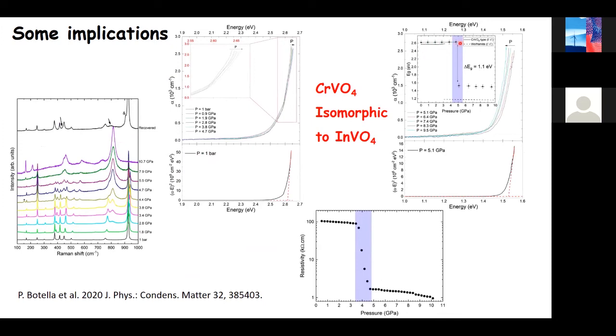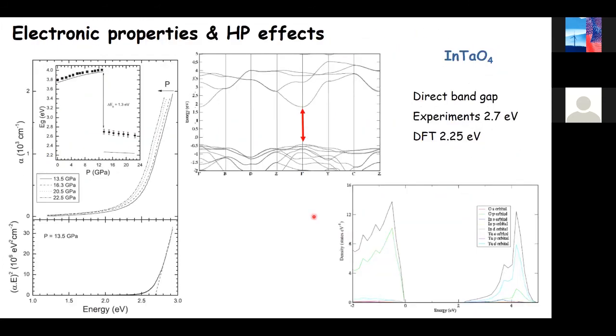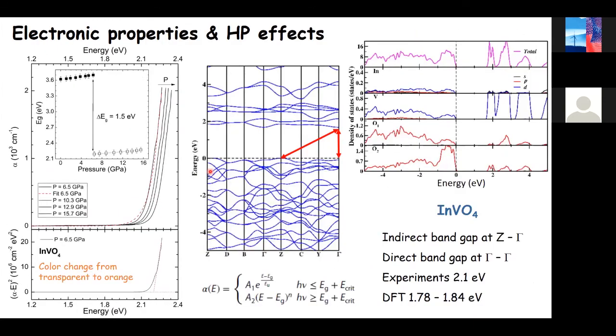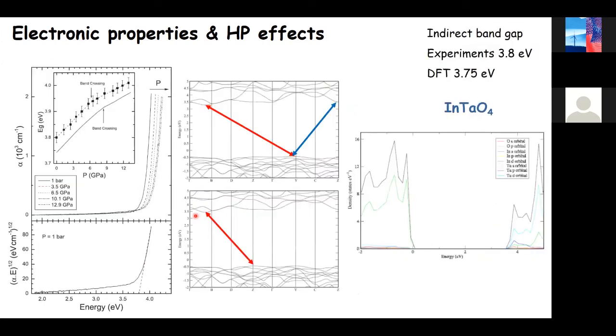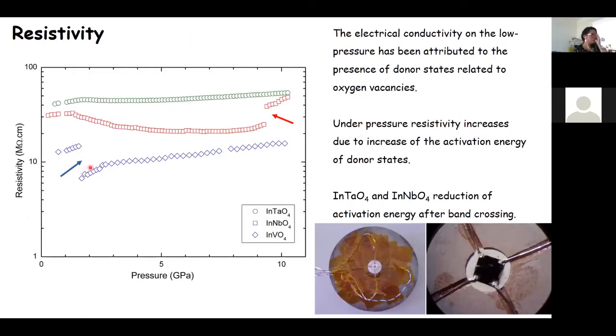The band gap is slightly increased with pressure in the low pressure phase because of the repulsion between bonding and anti-bonding states. And then when the phase transition happens and there is a change of coordination and an increase of the coordination, there is a collapse of the band gap. You can see it here, and you see here the change of resistivity. So you see this collapse, and you go back to indium vanadate, and you can see the same collapse in the band gap. And you go to the resistivity, and you also see the jump in the resistivity. So this happened in the two compounds.